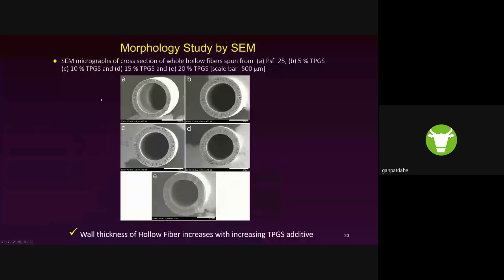This is the SEM micrograph of the hollow fiber, all five different types of hollow fiber produced from the setup. You can see that the wall thickness of the hollow fiber increases with increasing additives, which is quite obvious because the percentage solid content is increased.